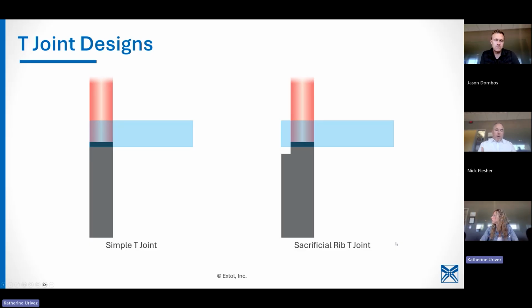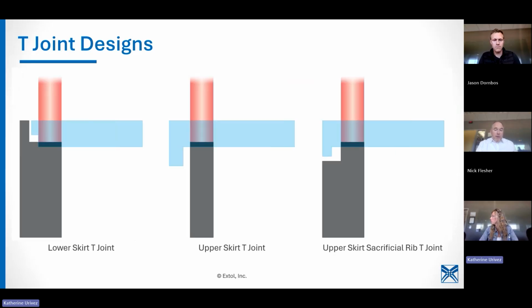T-joints, you've got some parts that are parallel to one another. A simple T-joint is not fancy, but no technology is flash free. You're going to have some amount of flash, but as you saw from those images, it can be almost imperceptible to someone who is not familiar. Sacrificial weld rib, this provides a really clean joint. You're going to have more flash in the absorptive material typically because that's where the energy is going first, then it's conducting to the upper. So usually we see more flash on the absorptive material.